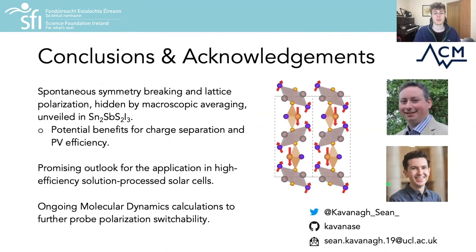So in conclusion, we unveil spontaneous symmetry breaking and lattice polarization in this emerging chalco-halide absorber through ab initio techniques, previously hidden due to macroscopic averaging in characterization measurements. This poses potential benefits to photovoltaic efficiencies, for example through enhanced charge separation and shift current effects. We determine a promising outlook for the efficiency potential of this material and propose that further work on this rediscovered material could prove very fruitful. To end, I'd like to thank my mentors David Scanlon and Aaron Walsh, and of course you for listening. Over and out.